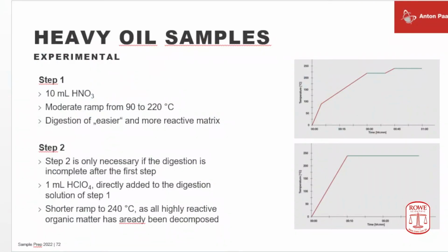Heavy oils, again, you have already seen such a profile before. A slow ramp, like I said, for the heavy reacting sample constituents, and a desired high final temperature for complete oxidation. It happened that some of these residues still looked very yellowish after this profile, and in such a case it's quite common to take the solution, add 1 milliliter of perchloric acid just as the final oxidizer, and heat up quickly to a temperature of 240 degrees. After such a 2-step procedure, any organic material would be destroyed up to perfection.